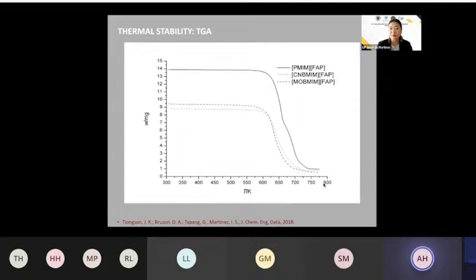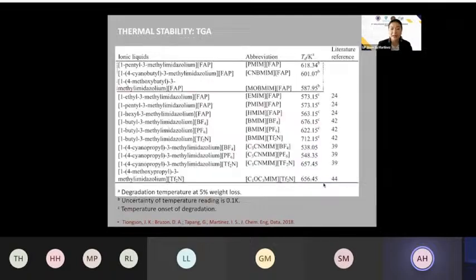And then in terms of the thermal stability, you can see here that the unfunctionalized ionic liquid is the most stable one. It's probably because of the saturated alkyl chain that's present. And then the lowest would be the methoxy functionalized one. And we think that it's because of the presence of an acidic terminal proton in the methoxy substituent, which led to its lower thermal stability. But compared to the other ionic liquids out there, you can see that our ionic liquids are quite stable. Of course, there are the TF2N ionic liquids, which are really very, very stable and the highest among these, and we still have to beat that.